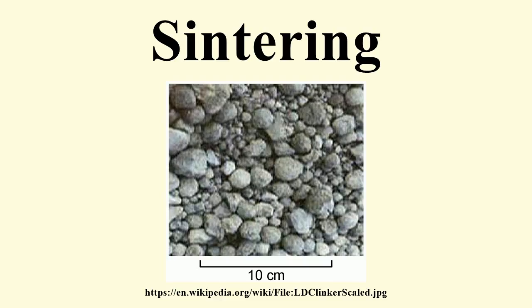In 1913, Weintraub and Rush patented a modified sintering method which combined electric current with pressure. The benefits of this method were proved for the sintering of refractory metals as well as conductive carbide or nitride powders. The starting boron carbide or silicon carbide powders were placed in an electrically insulating tube and compressed by two rods which also served as electrodes for the current. The estimated sintering temperature was 2000 degrees Celsius.